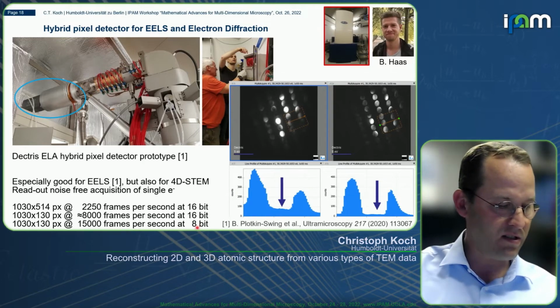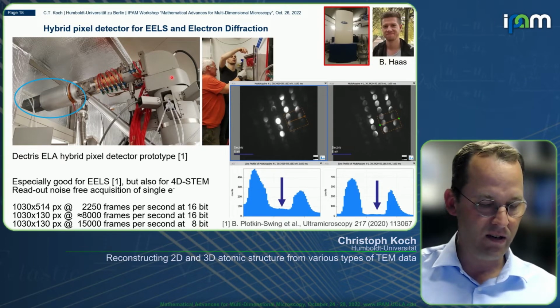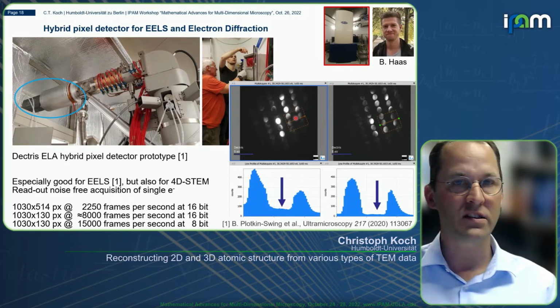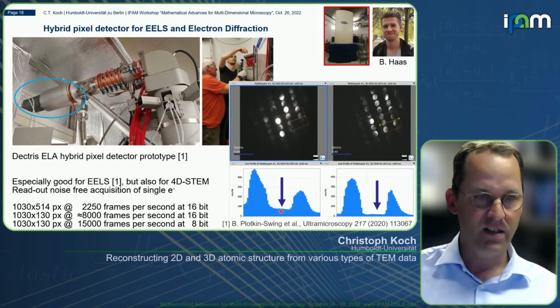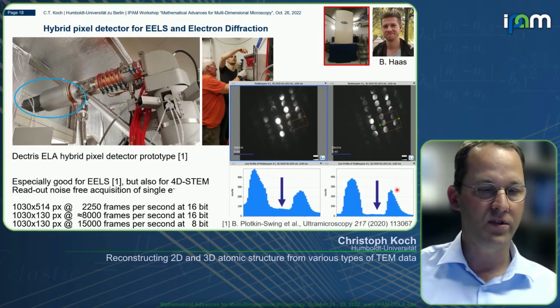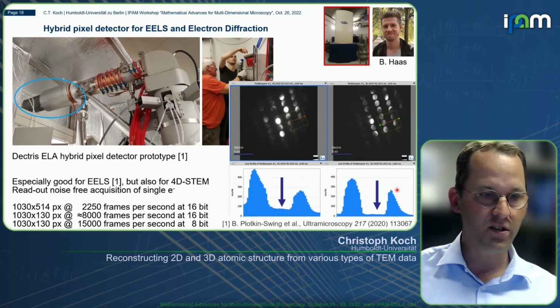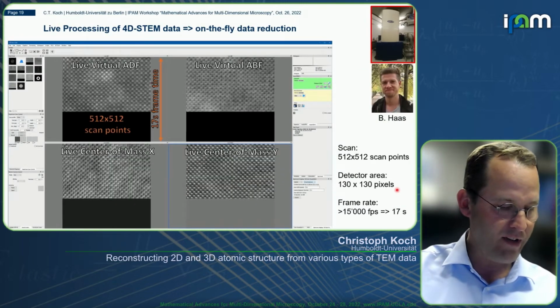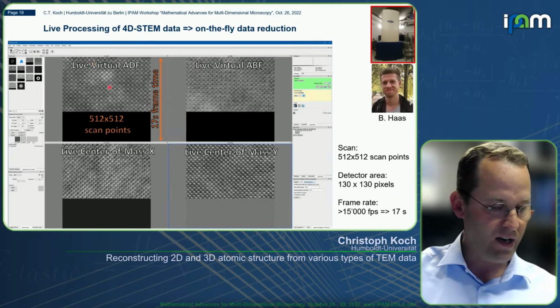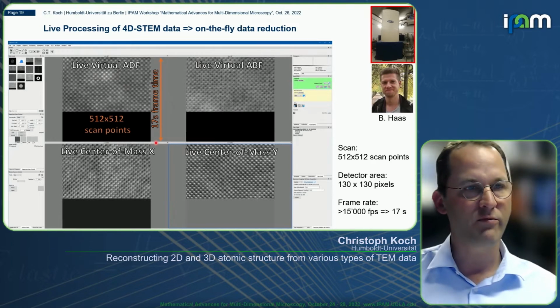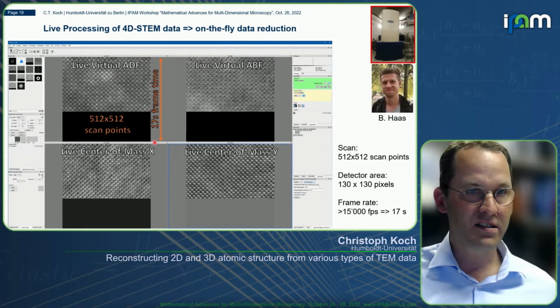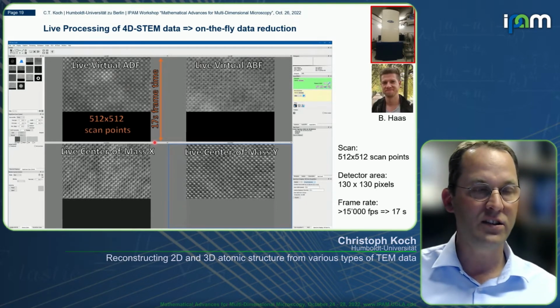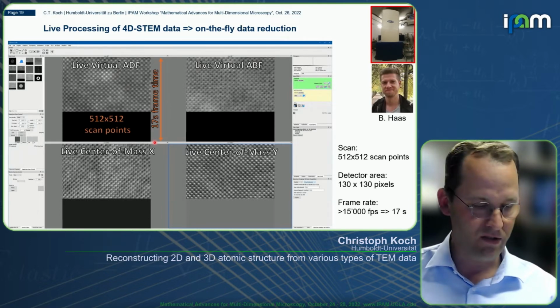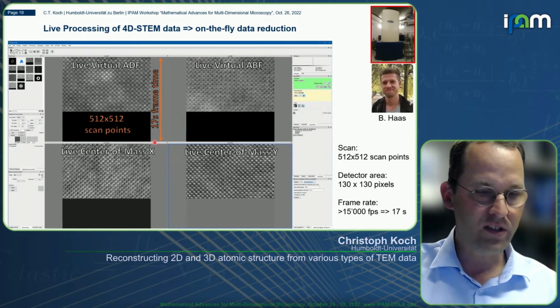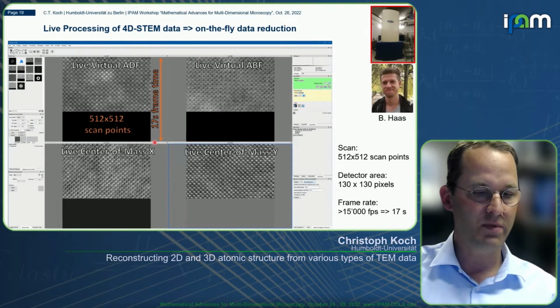And the nice thing about this microscope, because the detector is mounted behind the spectrometer, you can also run the spectrometer as an energy filter and remove a lot of the inelastically scattered electrons between your dark spots, which means that you now have data that is somehow more easy to model, because you don't need to account for this inelastic background in it. And because it goes very fast, you can also do live processing of it. For example, this scan of 512 by 512 points on this detector is acquired in 17 seconds, and you can do live processing, for example, extract the center of mass and apply not only these masks, but also all kinds of other masks to the data on the fly, and then only store basically this reduced information. I will come back to this, which is actually quite advantageous for many applications if you don't need to store tens of gigabytes of data.